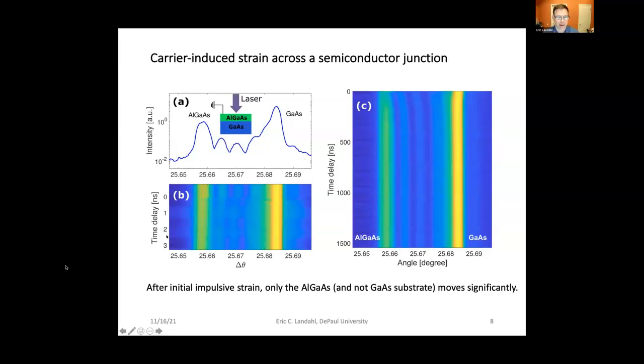Here in time, this is in nanoseconds. So over the first few nanoseconds, we see, as has been previously discussed, the rapid strain wave that comes from the sudden perturbation of the material. And so you see some wiggling of the strain waves as expected. But after that initial impulsive strain, interestingly, only the AlGaAs layer, shown here, undergoes modulation, whereas the substrate does not move significantly at all. And this is going out to very long time delays, the point at which thermal diffusion would set in.